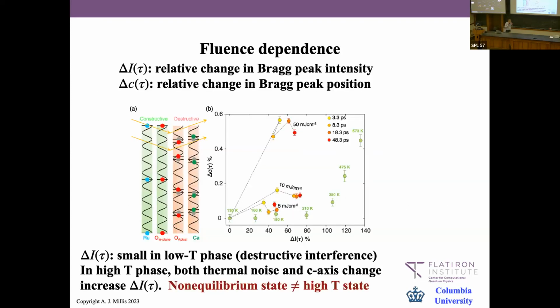Okay, now here's the final part, and this is slightly sketchy and will take a minute to explain, but bear with me. The knock on all of these non-equilibrium experiments is you hit the system hard, so you're dumping a bunch of energy into it. So the first thing you might think is, well, you're just heating the sample—and this is simply a very expensive and inefficient way to heat the sample back up to the temperature where it would be metallic anyway.